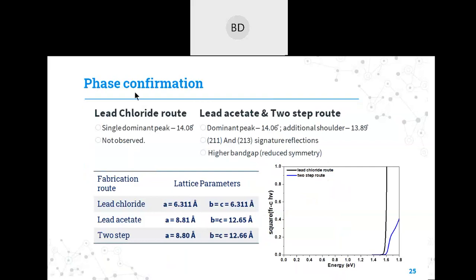Also, when we did the lattice parameter calculation, we came to know that the lead chloride forms a perfect cubic phase with lattice parameters of 6.3 angstrom, and lead acetate and two-step routes form a tetragonal phase with 8.8 and 12.65 angstrom lattice parameters. So this confirms that there is a phase difference between the lead chloride and lead acetate and two-step routes.